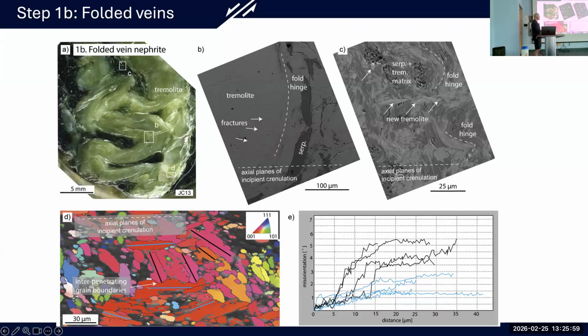And if we look at the misorientation, the degrees of misorientation within a given crystal, that is to say, looking across a profile of the crystal, looking at how misoriented every single point is with respect to the overall crystallographic orientation within that grain, we see that we have kind of two classes of grains. Grains with very little misorientation, a couple of degrees, and these tend to be aligned to our folds. And then we also see grains with a high degree of misorientation, and these are the ones that are acting as indenters or penetrating into the other grains. Again, this is indicating to us that we are dealing with a deformation process.